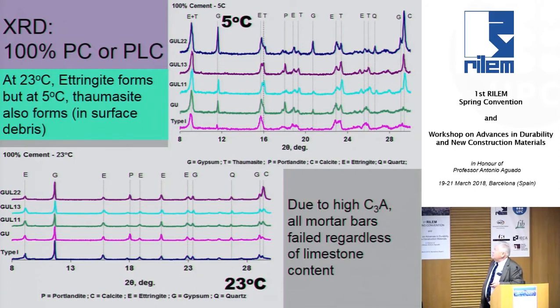And we did X-ray diffraction, amongst other things, and what we found was at 23 degrees, these are the 23 degrees with different amounts of limestone, we see ettringite, gypsum, portlandite, but at the low temperature we also see the doublets related to Thaumasite and ettringite. So the Thaumasite does form at the low temperature in the debris, not so much in the intact bar, but in the debris that forms in the bottom after the fact. And as we found later, the ettringite forms first, the failure occurs by ettringite, and then with prolonged exposure of the pieces, the small bits of debris, Thaumasite forms as a secondary reaction.